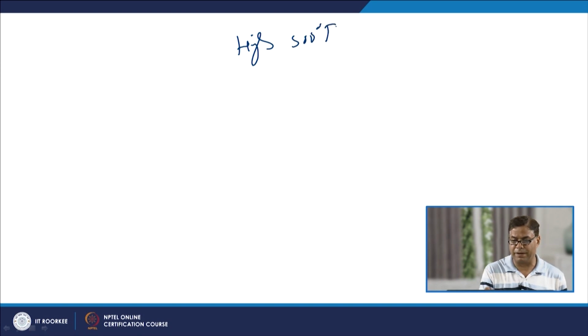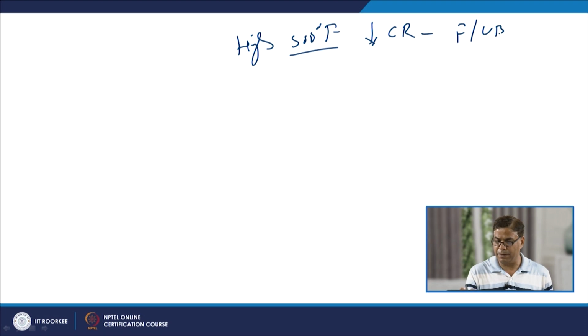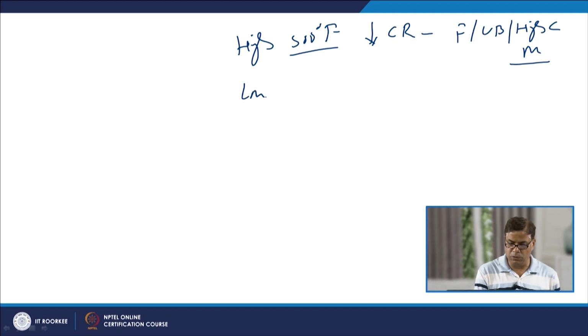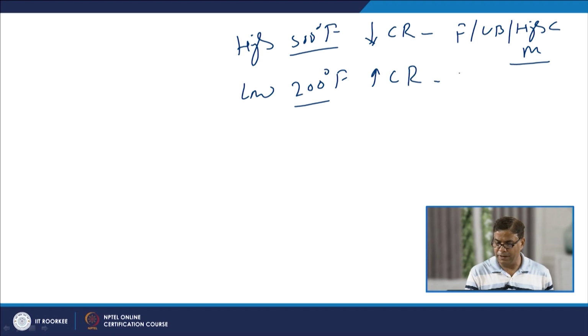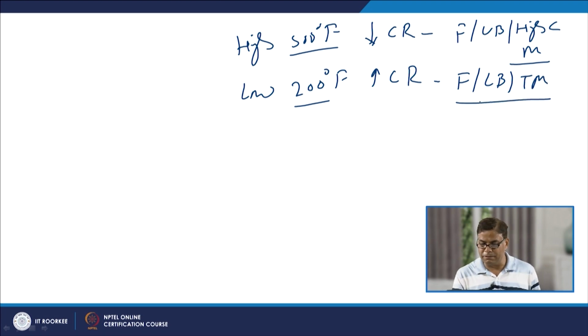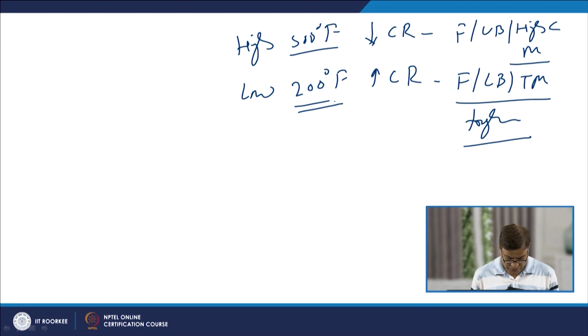And therefore, different values of preheat are used. Too high a preheat temperature, say 500 Fahrenheit, will lower the cooling rate, which will lead to the formation of ferrite, upper bainite, and maybe a high carbon martensite. On the other hand, a preheat of, say, 200 Fahrenheit will lead to a reasonable cooling rate and a good combination of ferrite, lower bainite, and maybe tempered martensite, and so we will get much better toughness when the moderate preheat temperature is used as compared to the case when a very high preheat temperature is used.